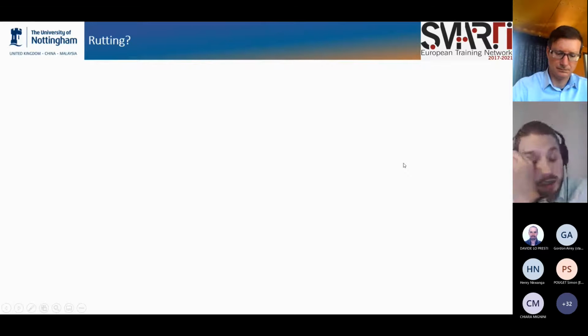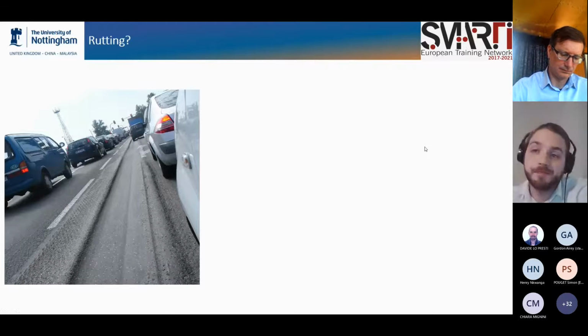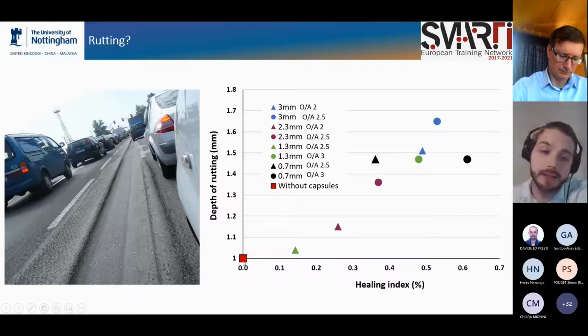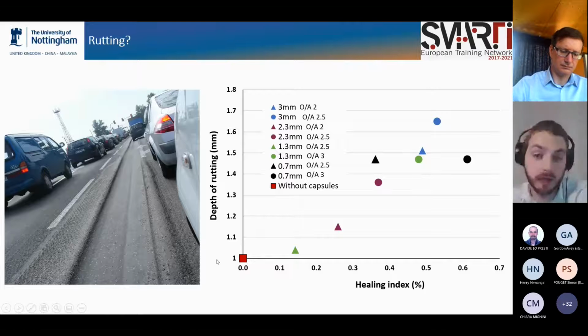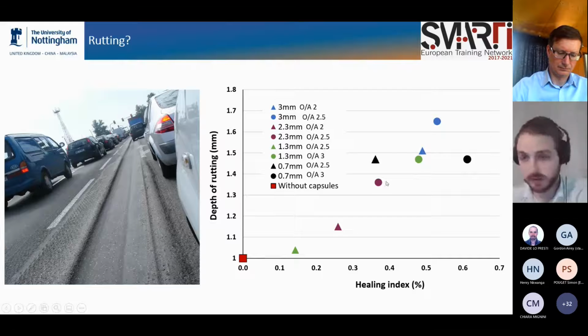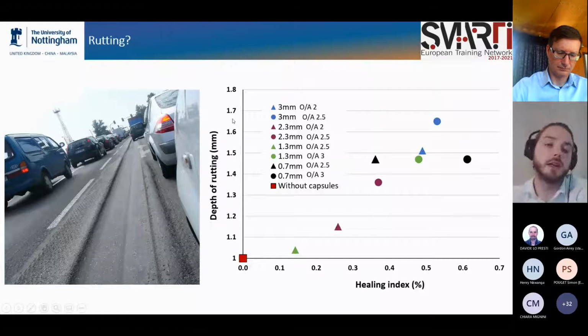Also, another question during the PhD was whether the oil released by the capsules is going to cause rutting. We can see this point here is the rutting obtained for a sample of asphalt without capsules, and this one here shows an increment of the rutting after the addition of the capsules. You can see a trend, but the increment is not significant for the road standards. 1.7 is acceptable, so we consider that the rutting caused by the capsules is not a problem.